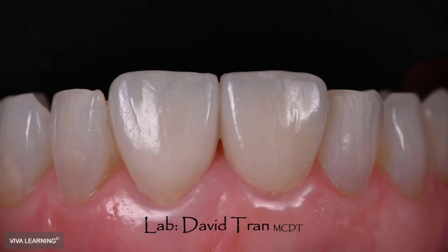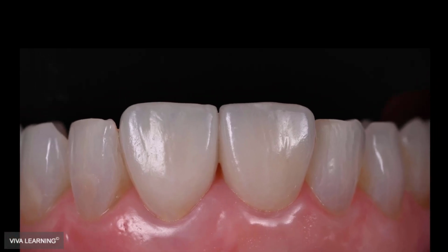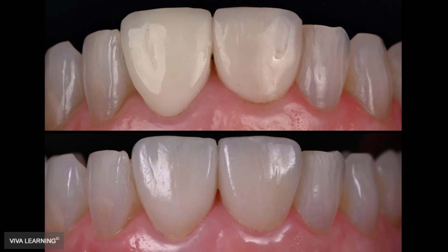And we can appreciate the fact that with the talent of the technician we have, and with choosing the right cement, we were able to match these two much better than what it was before. Let's take a look at what it was and what it is right now, so you can see that there was a clear mismatch between the opacity of these two restorations, between the shade of these two restorations, and now we were able to match them really better by choosing the right cement and choosing the right type of material. And of course, having a very talented lab tech being able to match them for us.